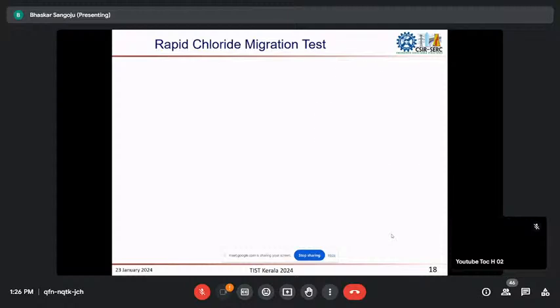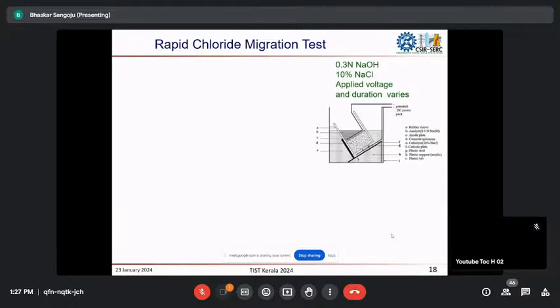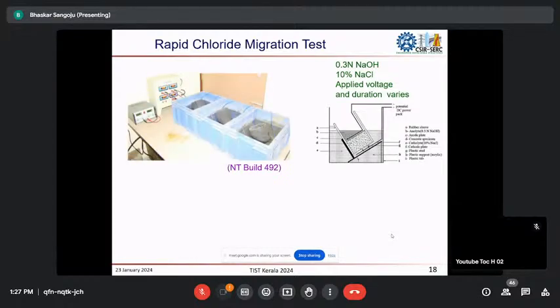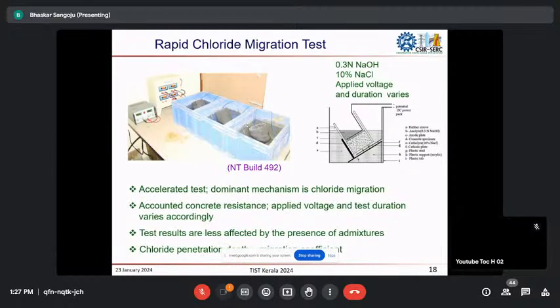Compared to the rapid chloride permeability test, the rapid chloride migration test is more reliable, because here we adjust the voltage with respect to the concrete property. So here the voltage is not fixed and the time duration is also not fixed. Of course, this is also an accelerated test, but 60 volts we are not applying here, whereas in RCPT we are applying 60 volt current. So sometimes the specimen may get heated, and other ions also may try to move, so thereby the total charge passed will get affected. So here that is not there.